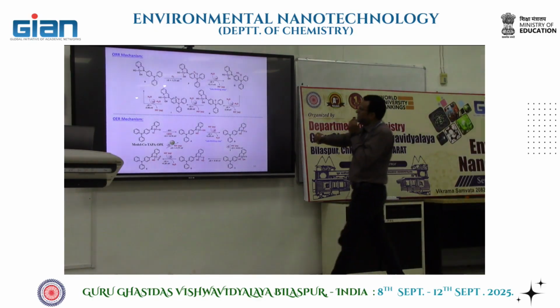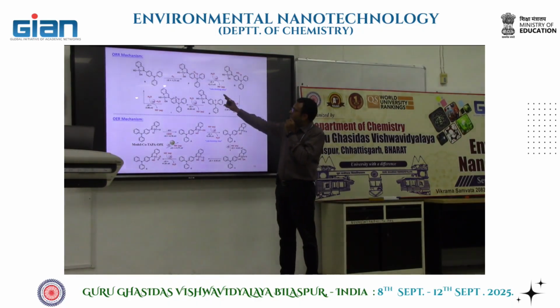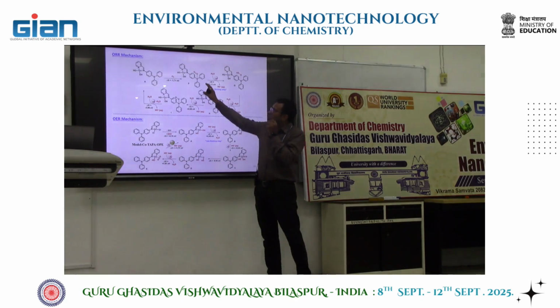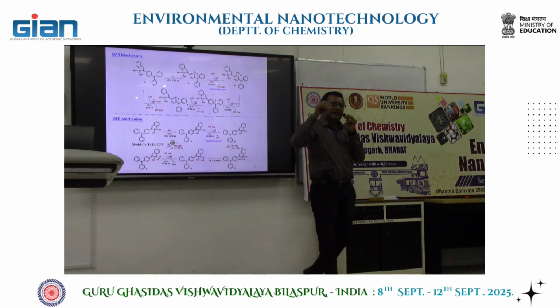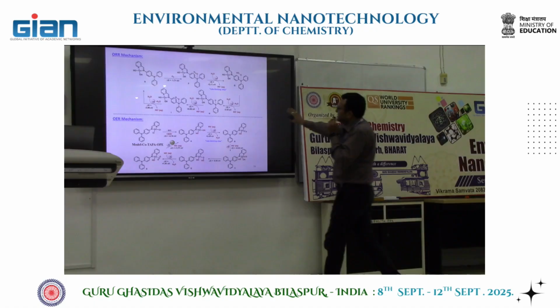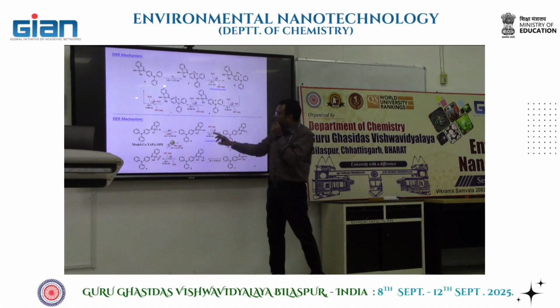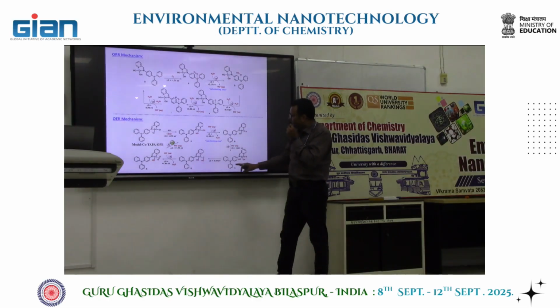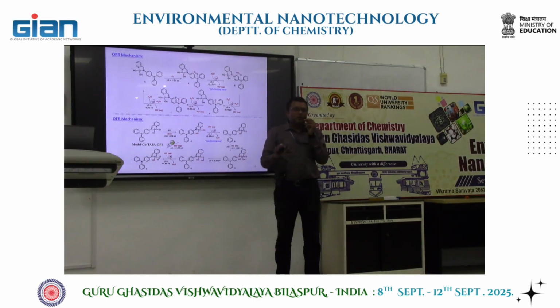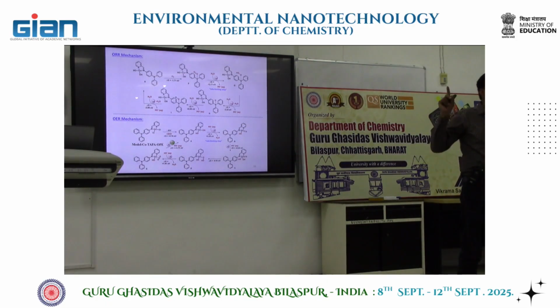So although cobalt is available, the oxygen remains with the triphenylamine due to the presence of the electron at the nitrogen center, and this is responsible for the oxygen reduction. However, for the OER, the water molecule goes to the cobalt center and it performs the OER. So it is again proven that both the individual properties are important to perform the bifunctional activity.